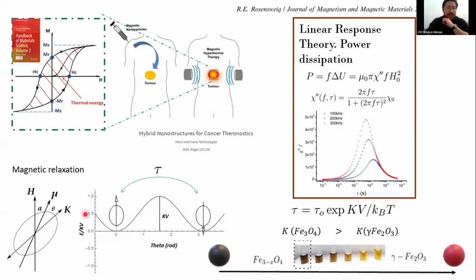And those stable states are determined by the system's anisotropy energy. For practical purposes, these systems are often considered to have a uniaxial anisotropy, defining two possible stable states separated by an energy barrier determined by the product KV, where K is the anisotropy constant and V is the volume of the nanoparticle.